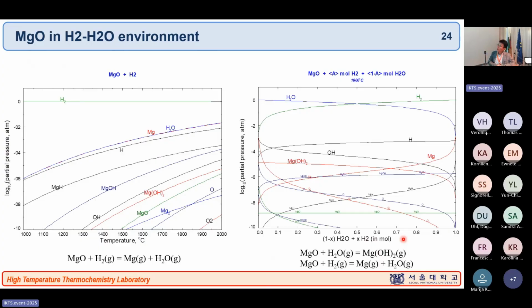Now let's move on to the refractory and the gas reaction. A lot of people are talking about hydrogen usage these days. So hydrogen is very important. On the left side, you can see the MgO and hydrogen chemical reaction with temperature, just pure MgO with pure hydrogen at 1 atm condition. You can see what kind of gas species can be formed theoretically in the thermodynamic condition. Here it is almost pure H2, as it is on the log scale.